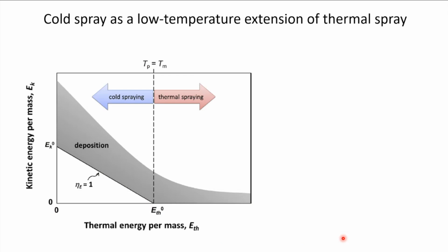So based on that, you can perceive cold spray as an extension of the thermal spray process towards the lower thermal energy regime. And you can actually build up a plot like this that tells you where you should expect deposition based on the kinetic energy and the thermal energy. But the main problem is, what about the mechanical properties? If your particles are harder, what happens then?